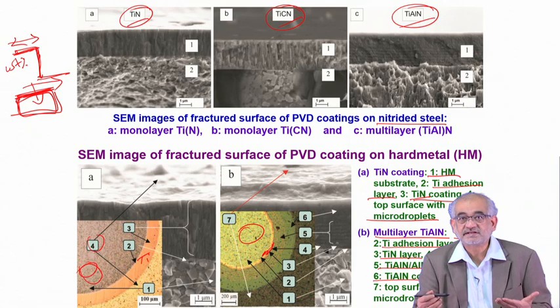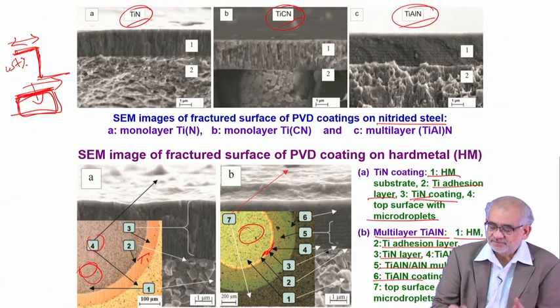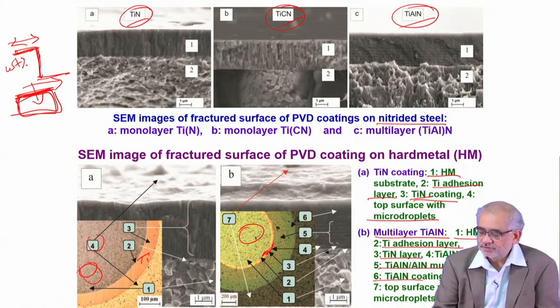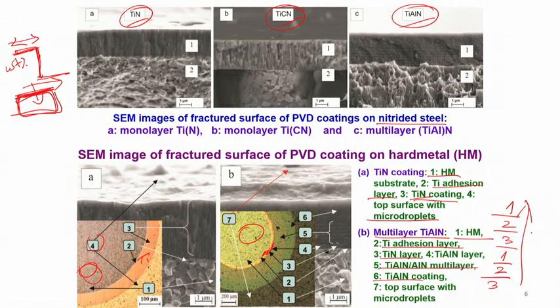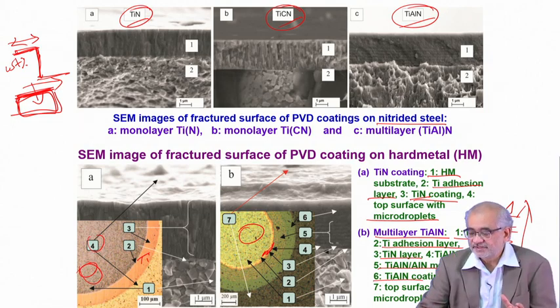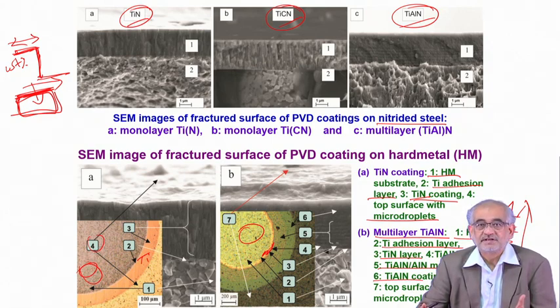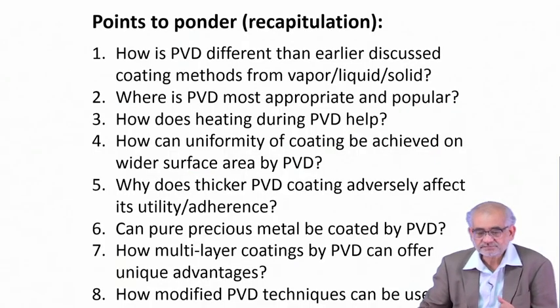To have such combinations of exotic coatings — steel, nitrided, with titanium nitride or titanium carbonitride or titanium aluminium nitride on top — PVD is essentially the only viable process. By using alternating multi-layers you can minimise the coefficient of thermal expansion mismatch, which depends on the relative thickness, composition, lattice parameter, and other physical properties. Such multi-layer thin film coatings will perform better under aggressive conditions.